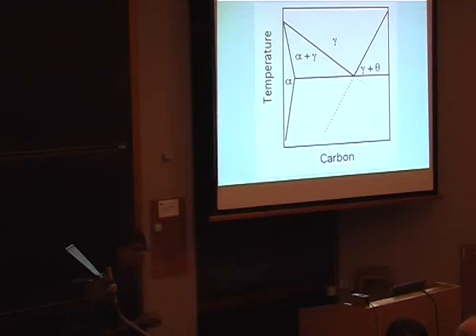But I have problems, because I want to do the phase transformation at a very low temperature. And I need thermodynamics to do the calculations. And of course, for the equilibrium region, there's no problem. I can get phase diagrams and thermodynamic data. But we want to transform at temperatures which have never been done before. And that means that we need to extrapolate these phase boundaries.